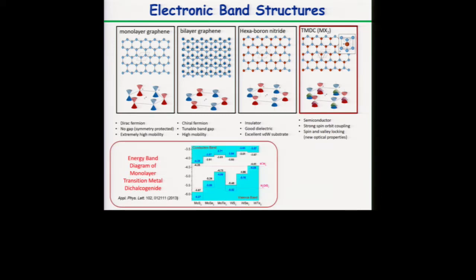As I said, graphene is one of those building blocks, and it's a semi-metal. It's a Dirac fermion at the end, right? There is no gap. Bilayer graphene has a gap tunable with electric field. We have hexagonal boron nitride, which has a large gap. It's an insulator. It's a good dielectric. It's a perfect dielectric, right? Layer by layer dielectric. We also have the semiconducting TMDCs, which have a visible gap, so we can couple them with light. That's also the importance of these materials. And also, they have strong spin-orbit coupling. They have this spin and valley locking that maybe I will mention later.